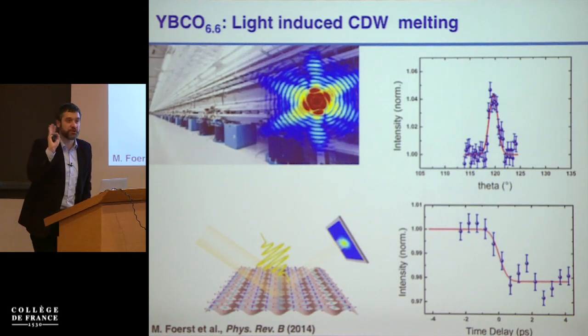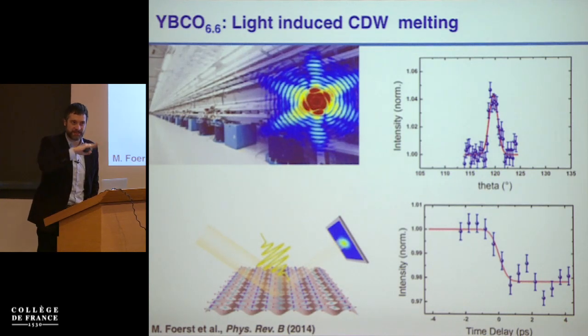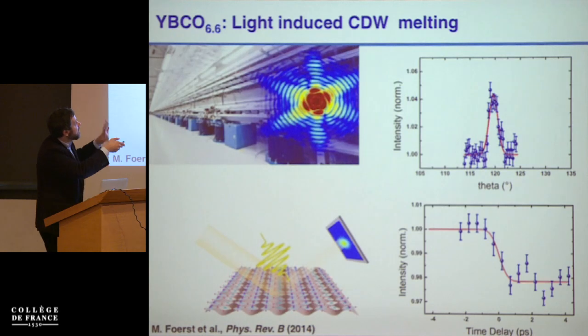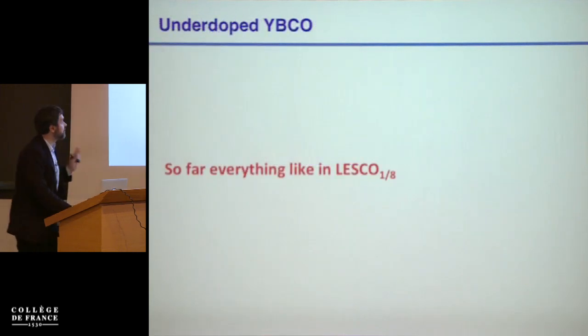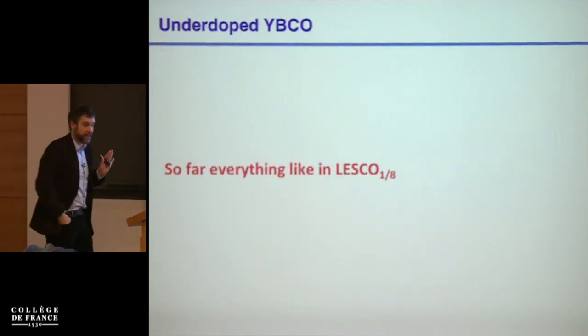Spectral weight transfer between the two junctions notwithstanding. Okay, so that's of course an additional piece of information, but in terms of the fact that you can observe this effect all the way to charge order, which in this case is 150 Kelvin, as opposed to 80 Kelvin in the other case, and that the melting of this order by, okay, this should be 40% of this peak, look at this, anyway, so this is almost the whole peak that is being melted, etc., etc. Okay, so far everything is like in LESCO 1/8.